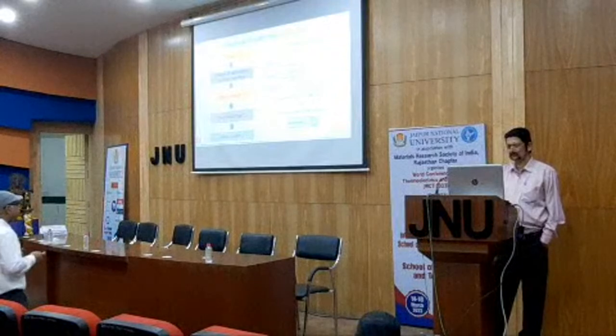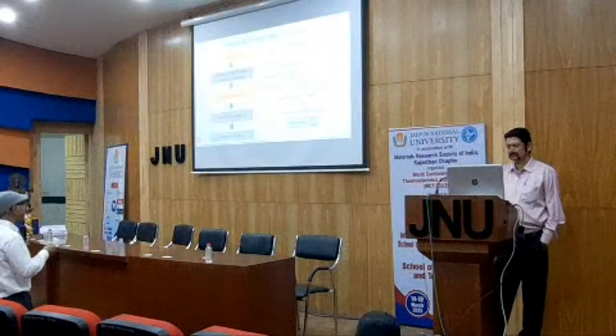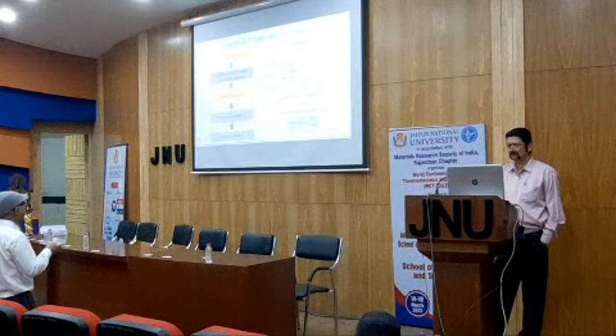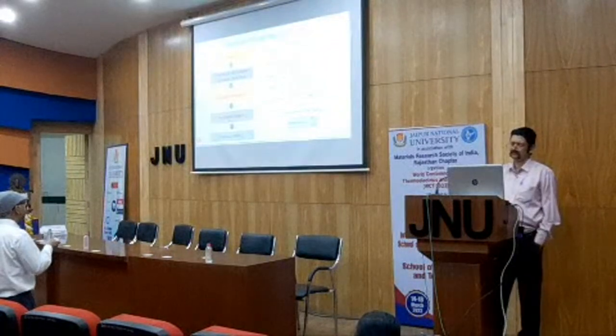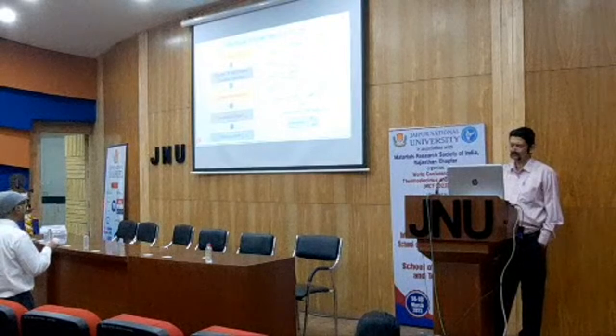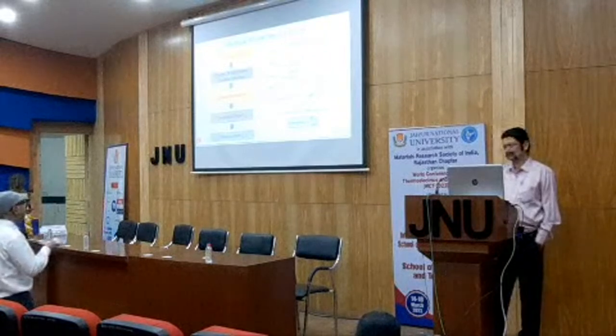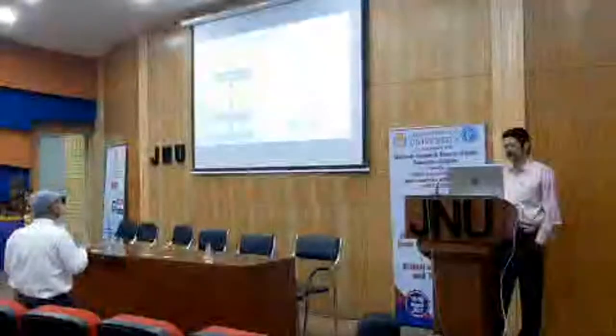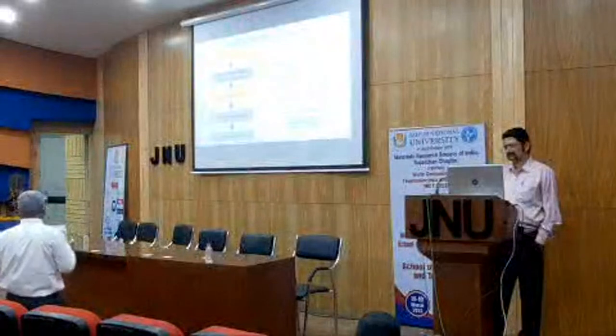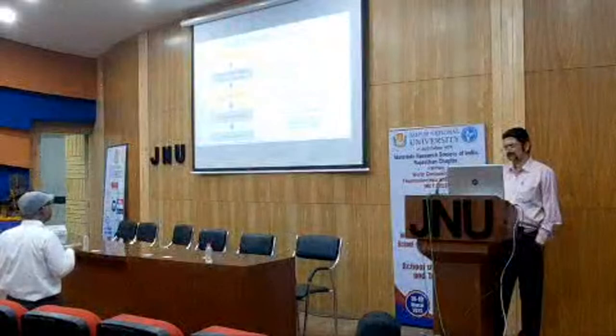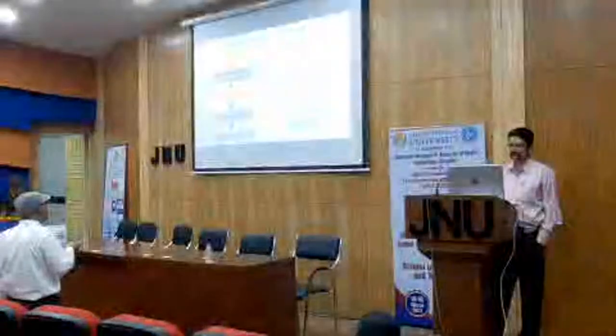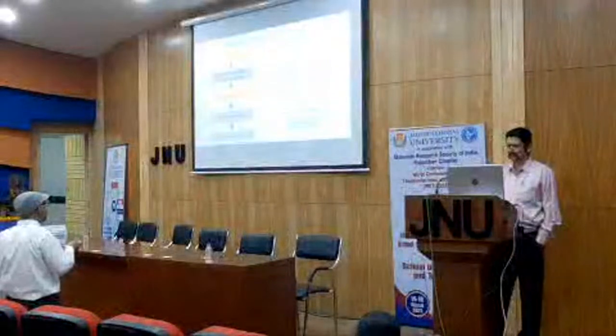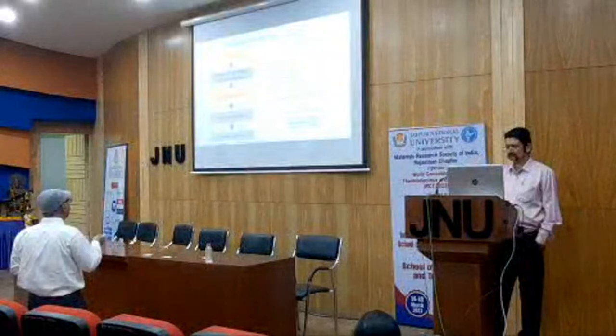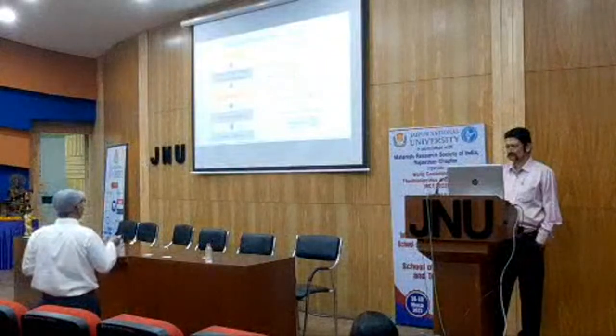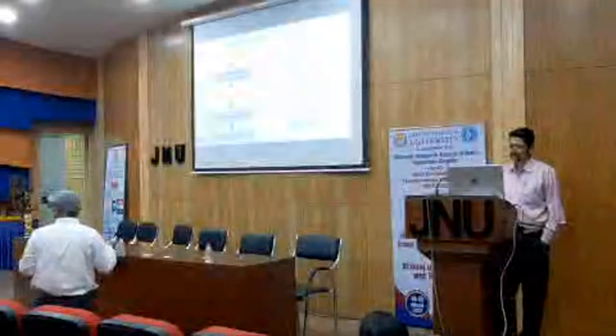You can see on the x-axis we have the reference electrode, the electrode through which potential is applied, and for different pH solutions, to get a drain current of the same value, we need a constant current, constant voltage philosophy. Why? Because we are applying a constant voltage, meaning VDS, the drain-to-source voltage, is fixed, and we are measuring constant current. Taking the pH buffer solutions 4, 7 and 10, we measure this difference and divide it by the difference in pH, for example 7 minus 4 is 3, or 10 minus 7 is 3. So we get a delta V reference, which is called the sensitivity, around 50 millivolt per pH or 59 millivolt per pH. Like this we calculate.